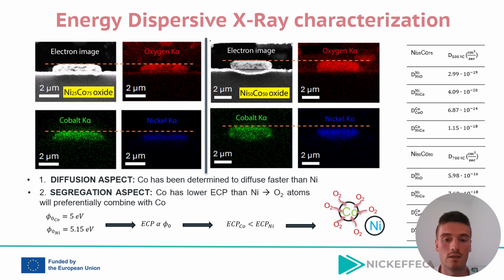On the other hand, the segregation viewpoint states that due to a lower effective electrochemical contact potential, cobalt preferentially reacts with oxygen atoms as compared to nickel.